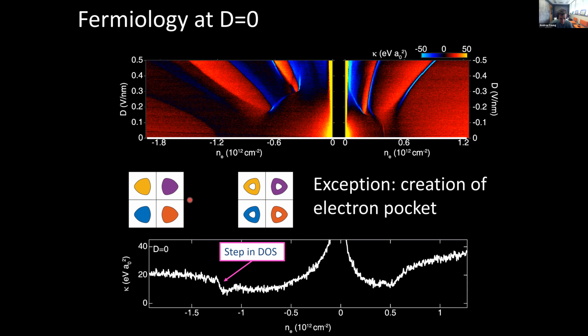And what I'm drawing here, and I'll use these schematics throughout, so let me just explain them, is that in graphene you generally have 4 flavors of electron. Because you have your spin degeneracy, but then you also have the degeneracy between these inequivalent Dirac cones at the corners of the hexagonal Brillouin zone. There are actually 2 of them. So that gives you 4 spin and valley flavors that you can occupy, which are roughly symmetric, not perfectly. The wave functions are not exactly the same, but you can think about an SU4 spin or isospin that emerges from the combination of those 2. And so when I draw these, what I mean is that when we don't have any ferromagnetism, you have basically 4 pockets that are equally occupied in the different spin and valley isospin flavors, and then all of them undergo this Lifshitz transition where you nucleate a new Fermi surface inside the large Fermi surface.